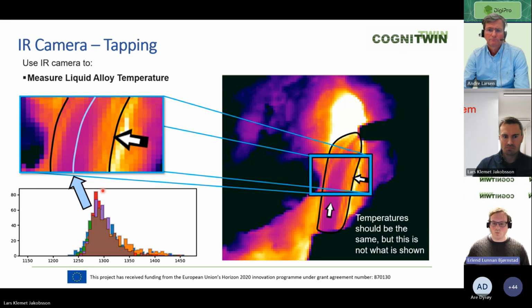So when you tap from the furnace into the ladle, the temperature is a very important process parameter because it determines essentially what we can do with the liquid in that ladle. So how we can refine it and how we can alloy it before we cast it. So this temperature budget is critical.